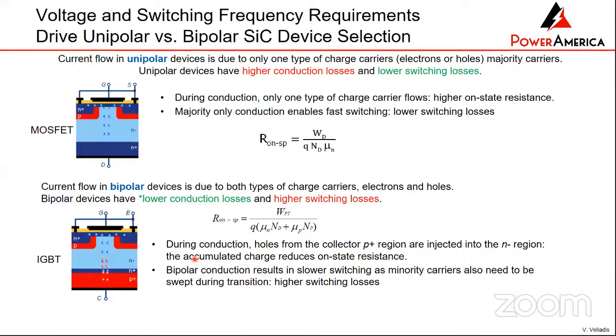So the bottom line is, if you make a device as a unipolar device, as shown here, you only have one type of carrier, your conduction losses will be a little higher, but your switching losses will be very low because switching is fast. If you make a bipolar device, then you have both electrons and holes doing the conduction. So that means the resistance is lower, but your switching losses are higher.